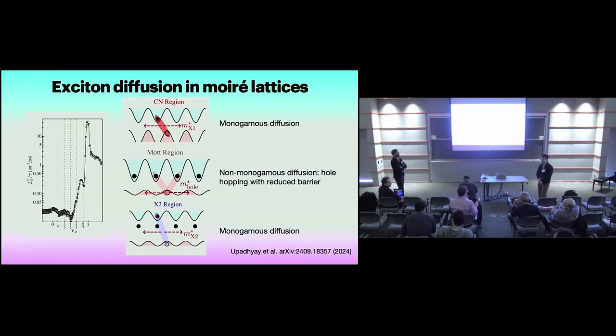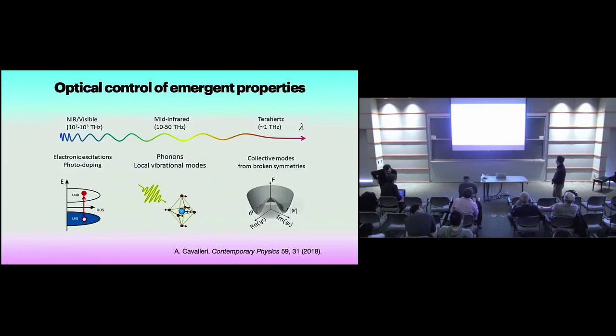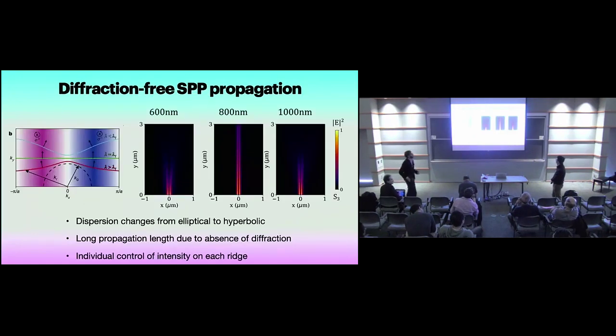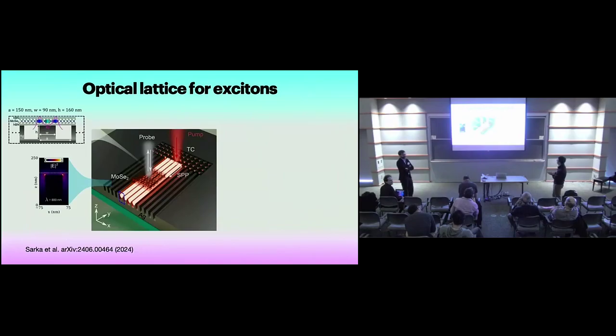This might be a naive, non-exciton expert question, but can you probe these plasmon polariton excitons that would, for ordinary light, be dark? Because they're either momentum mismatched or polarization mismatched. Yeah. So this is actually something we put into our proposal. You can see here, in the near field, this is really tightly confined. So if you do a Fourier transform, this corresponds to very large momentum. And we are very interested in momentum dark states. People have looked at spin dark states, but not momentum dark states. This could potentially enable the study of momentum dark states.